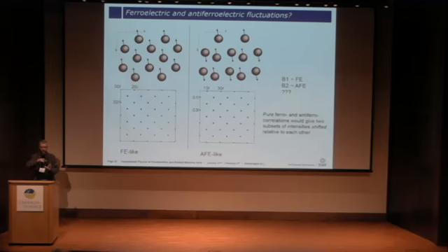If you start to displace the ions in antiphase, which can remind of antiferroelectricity, you will create the shifted mesh, something which reminds of the B2 component. And it looks like, okay, I oversimplify the picture, that the B1 component is responsible for ferroelectric-like fluctuations, and the B2 component is responsible for the antiferroelectric-like contribution.